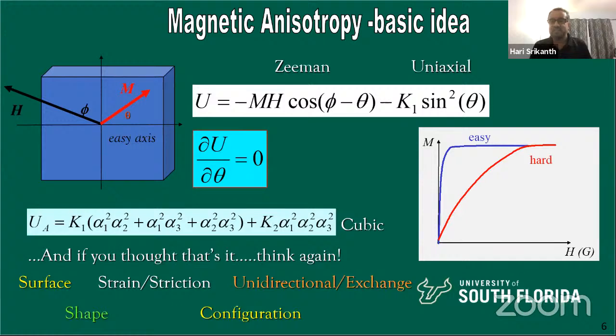You see that you have an easy axis if you can magnetize it very, very easily at very small fields, then you have a shape that looks like that. And if it's hard to magnetize it in a different direction, because the anisotropy energy is dominant, then you see that the shape is something like that. So this determines the easy direction, the hard direction, soft magnets, hard magnets. There are many applications depending on the shape of the MH curves, the so-called hysteresis loops, okay?